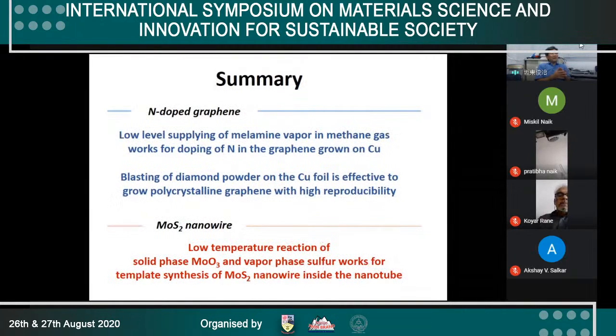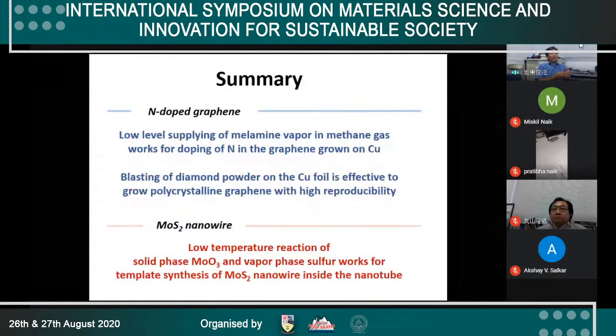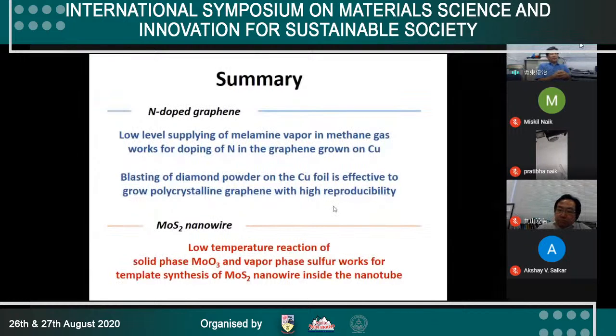This is the summary of my presentation. Low-level supplying the melamine vapor in methane gas works for doping of nitrogen in the graphene grown on copper. The blasting of diamond powder is effective to increase the reproducibility, and the low temperature reaction of solid phase MoO3 and the vapor phase sulfur works for template synthesis of MoS2 nanowire inside the nanotube. Okay, this is my brief result of my research. Thank you for your attention.